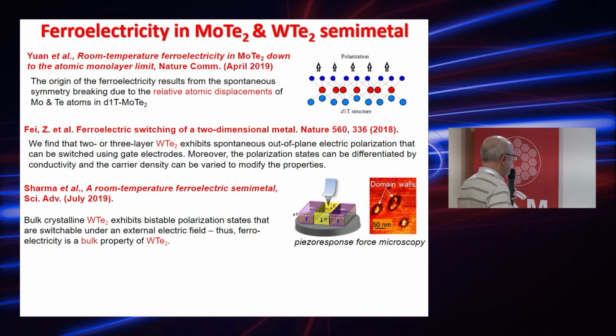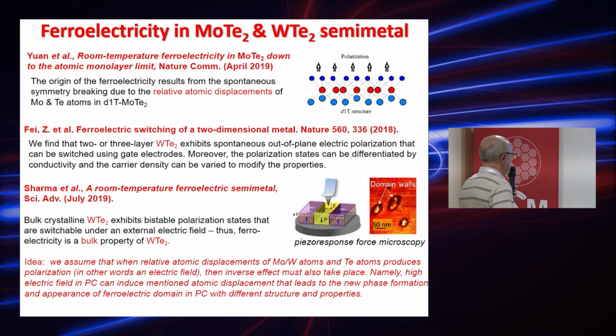Taking this paper into account, we came to the idea that when the relative atomic displacement of molybdenum or tungsten atoms and tellurium atoms produces polarization, in other words, electric fields, then the inverse effect must also take place. Namely, a high electric field in point contact can induce the mentioned atomic displacement that leads to new phase formation and the appearance of an ferroelectric domain in point contact with different structure and properties.